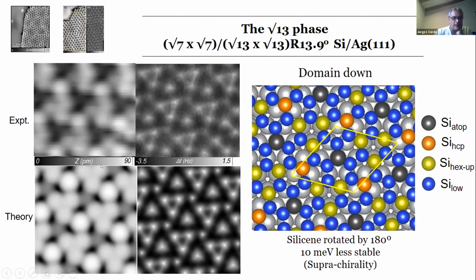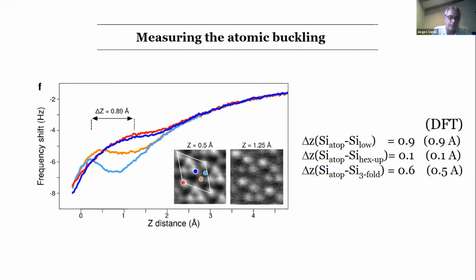Again, the simulations are very similar as before. Nothing really changes, but the triangles are really pointing down this time. Again, we can see the features as before. And now when we want to measure the corrugation, it's not so direct as before. We have to do some fittings to potentials. I can show you later if you want to. But for the buckling, we still got an almost perfect agreement against DFT. It really shows that this way of retrieving the atomic bucklings is working perfectly for this system.